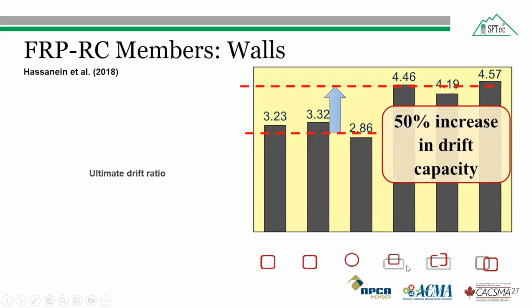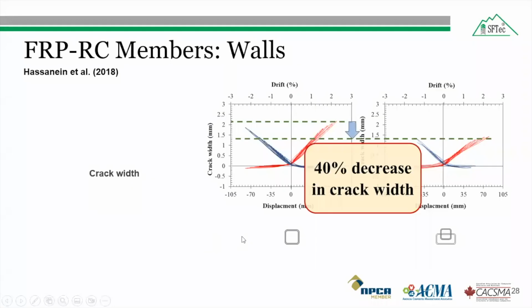As you can see here, the confinement was doubled in these 3 shear walls, and there is an increase in the drift capacity by 50%. The crack width of the shear wall with the more confined boundary element was decreased by 40%.